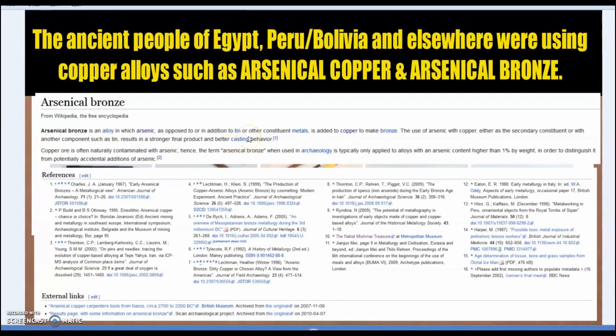It's strong. Now, for instance, the steam engines, the old trains, they would specify arsenical copper for use in the boilers to add strength. Bell casting and early cannon casting, they would use a tin bronze, but they would add arsenic to improve the casting behavior. Hence the term arsenical bronze when used in archaeology is typically only applied to alloys with arsenic content higher than 1% by weight in order to distinguish it from potentially accidental additions of arsenic. So arsenical copper less than 1%, arsenical bronze more than 1%, and means that it was added intentionally.